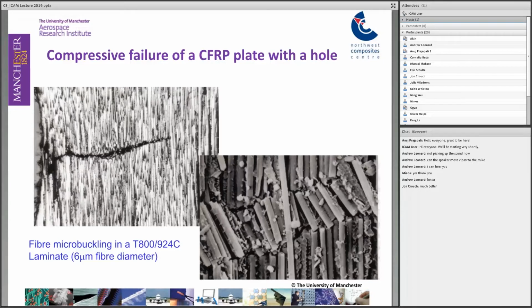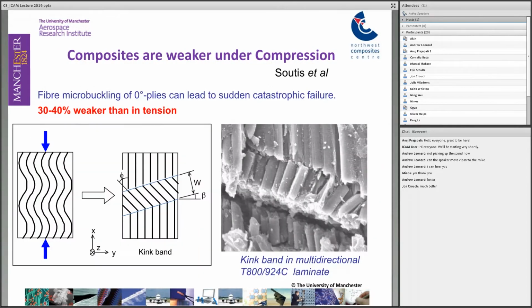And if we go to SEM, scanning electron microscope, we're going to see that that crack is in the form of fiber microbuckling in the zero plies, which carry the actual loading. And those microbuckles, obviously, are a fiber instability failure mode. When it reaches a critical strain, they break and the crack grows in an unstable manner, causing catastrophic failure. So here we can see the schematic and the SEM micrograph that shows the fiber microbuckling of the zero plies. And that reduces the compressive strength by 30 to 40% when compared to the equivalent tensile strength for the same laminate.